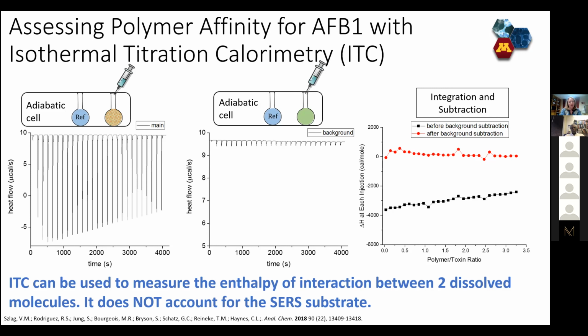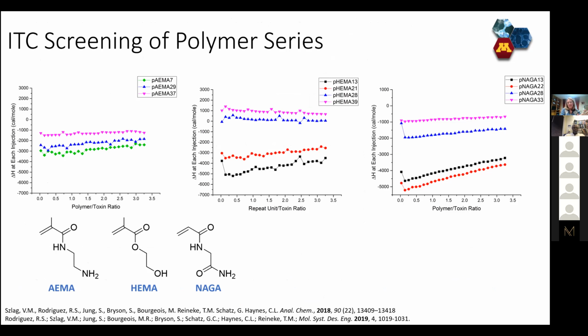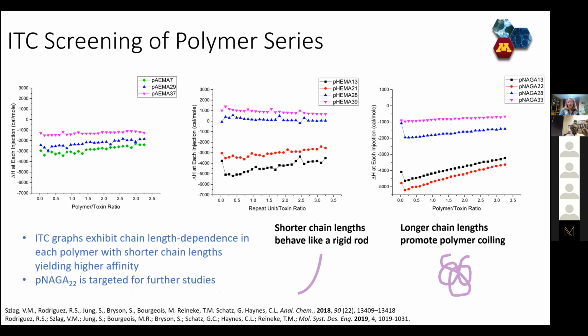So we went through and did this, and sorry, there's so much data on this slide, but what you're looking at are these heat of interaction plots for the 3 different polymers. So the AEMA on the left, the HEMA in the middle, the NAGA on the right, 4 different chain lengths for most of them, the numbers telling you how many monomers are in the chain. And what's really obvious from this plot is that the shorter chain lengths had a stronger interaction with aflatoxin B1. You can see they've got bigger delta H's, the red and the black lines. And so what we saw, shorter chain lengths seemed to be the way to go. And specifically, we picked out the poly NAGA with 22 repeat units. You can see that's the red line in the far right plot there, as targeted for our further studies.